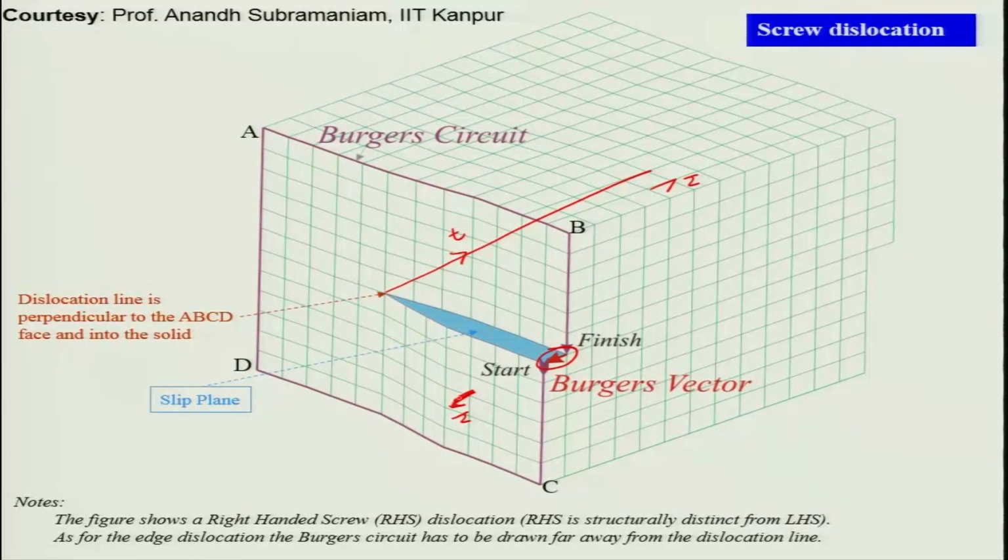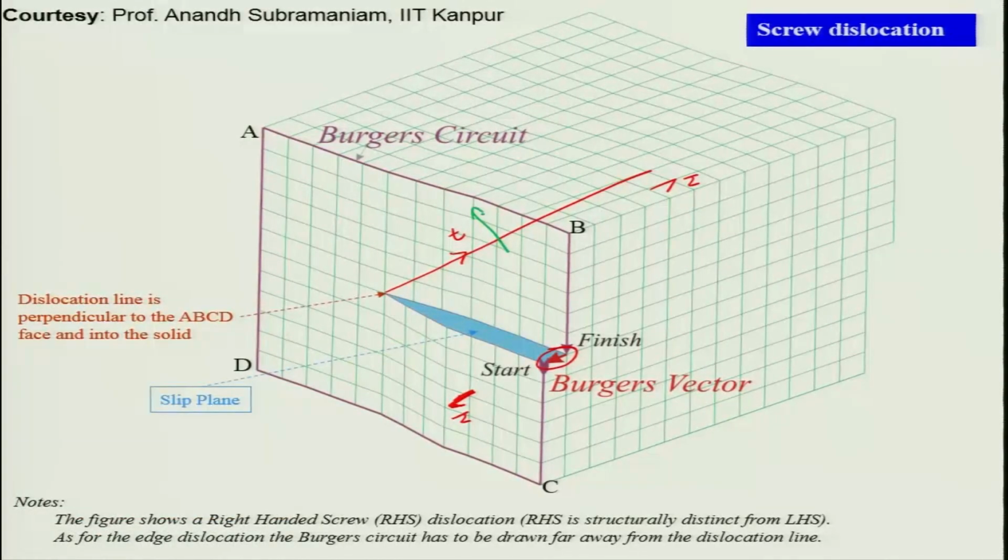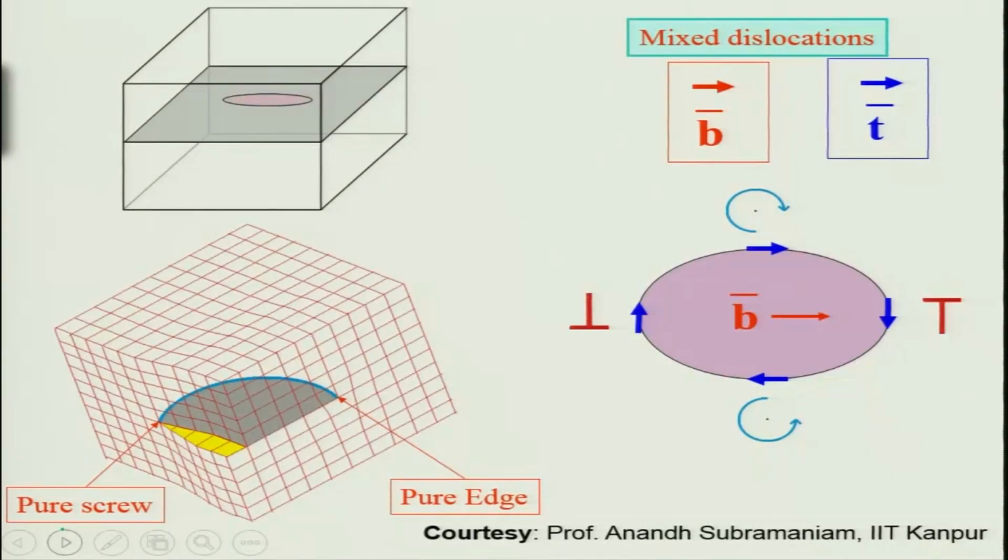Okay. So, this is the stress direction. When you apply stress in this direction, the dislocation line is going to move in this direction. So, this is the motion direction of, let us say, T. T moves perpendicular to the applied stress, and as a result this motion is also perpendicular to the Burgers vector. When you keep moving it, it will become a perfect crystal and you create a step.